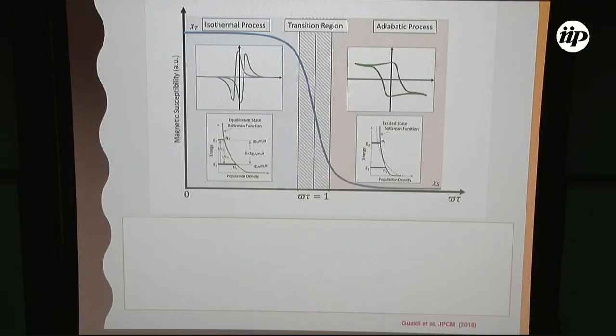So, in this process, it is possible that two processes occur when an AC field is applied to the sample. In the limit of low frequency, an isothermal process is observed in this behavior of the magnetocaloric effect, and with increasing frequency there is a change to an adiabatic process of the sample. It is a change of the equilibrium level of the state. In the case of the isothermal system, the density of the population is in equilibrium like a Boltzmann function.